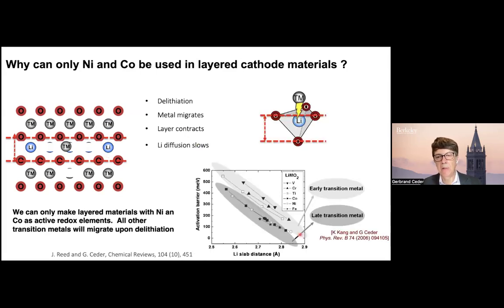And that's shown here in an old calculation we did. This is actually the activation energy for lithium motion as you contract the slab space. And this is a dramatic effect, right? Even like 1/10 or 2/10 of an angstrom raises the activation barrier by several hundred millielectron volt, which would basically mean the difference between lithium mobility and nothing at all.